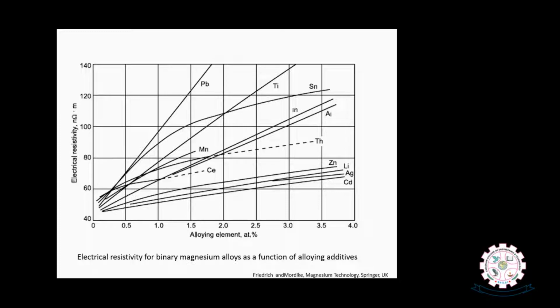For example, here you can see in binary magnesium alloys, different alloying elements, how they affect the bulk properties of the alloy. Couple of properties we will see here. For example, here electrical resistivity is highly influenced by the alloying elements. For example, if you take lead, like titanium, right? So here you can see too much variation, too much change in the electrical resistivity with a minute increment of the alloying elements. There are other alloying elements like zinc, lithium, cadmium. They have insignificant effect on electrical resistivity even if we change a good amount of alloying element.